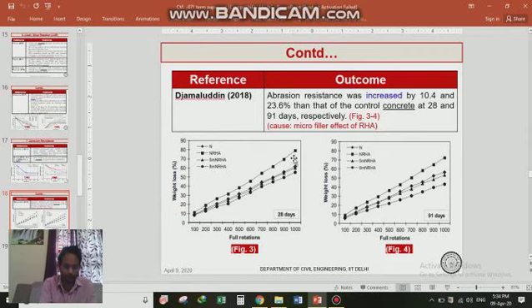This is for control concrete. This is for non-processed RHA, and this is for ground RHA, 5 minutes, and this is for rice husk ash ground up to 8 minutes. It was concluded that weight loss decreased as the fineness of RHA increased from top to bottom. Similarly for 91 days also.